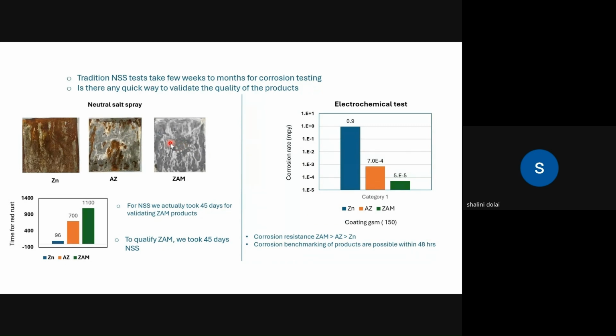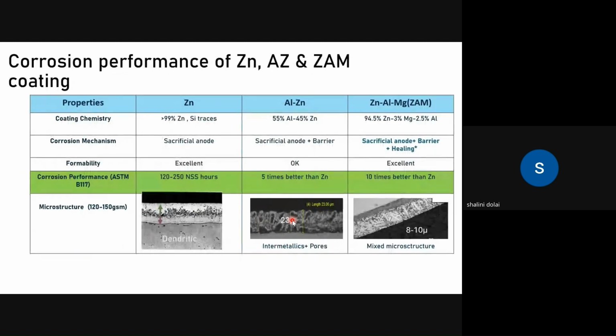We cannot quantify it. So we went ahead with the electrochemical test where we can calculate the corrosion rate directly, and here I can clearly tell it is much better. I can quantify the corrosion rate here. So this was one case study, and I explained all of this, so I'm skipping it.